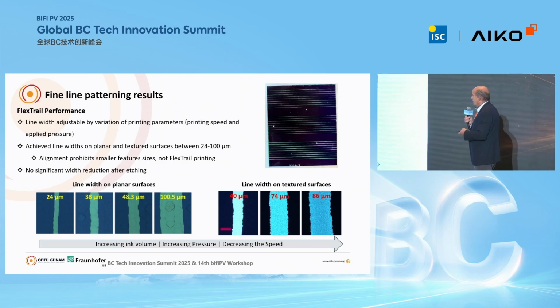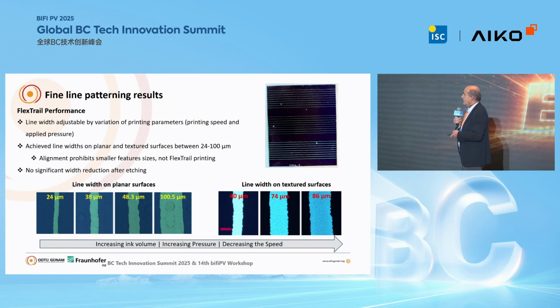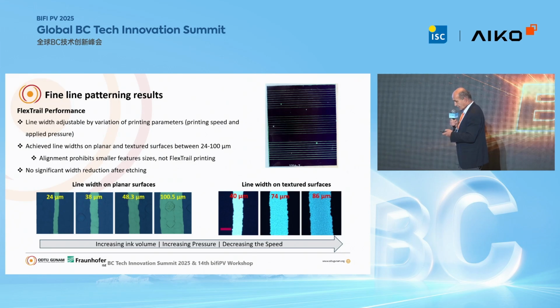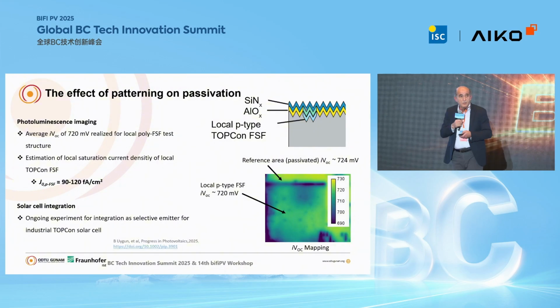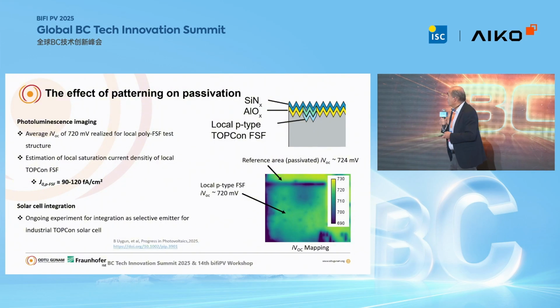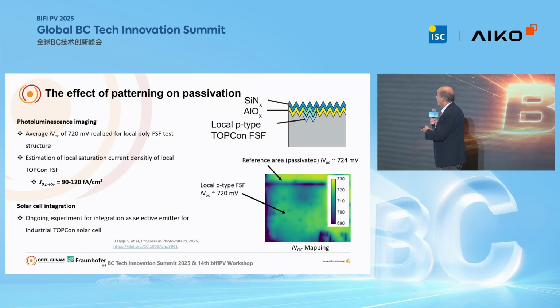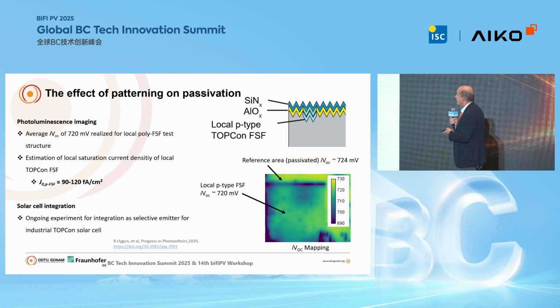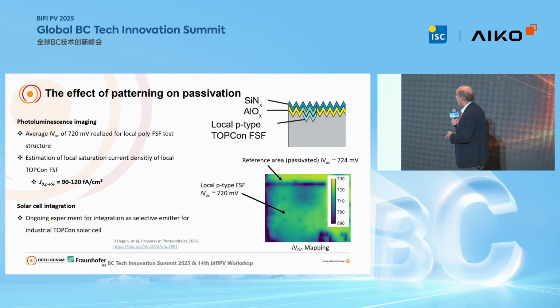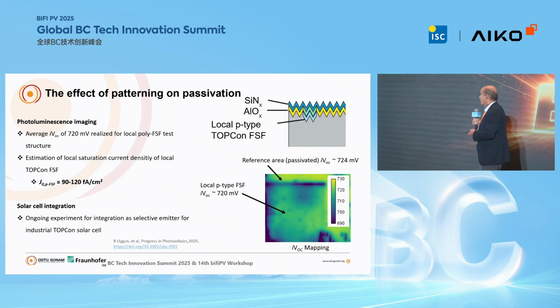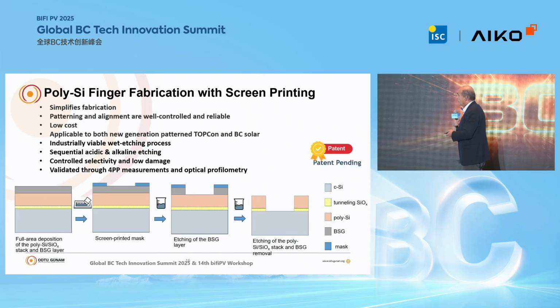So there is no undercutting. The masking is working quite well. So the widths can be obtained in this way. I mean the polyfingers. Well, of course, the passivation is an important problem in here. So we have obtained an average passivation of around 720 in this structure, in the pattern structure. And from this PL image, you see the passivation is quite all right. I mean, it can even be further improved, of course, but the values are still good for such a structure.